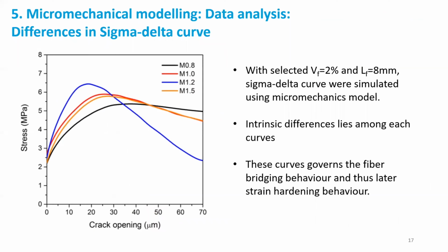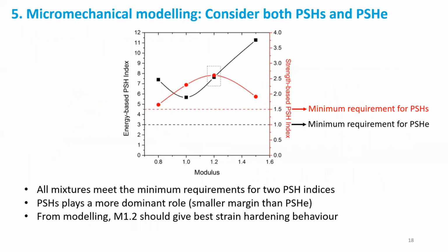Afterwards, we incorporate these two values along with the interface and the matrix properties, and we use micromechanical modeling to calculate the sigma-delta relationship. You can already see that all of the mixtures have very intrinsic differences among them, which means they should have different strain hardening behavior. We also calculate both PSH indices for all mixtures. As you can see here, all mixtures at least meet the minimal requirement for the two PSH indices. However, it seems that the PSH strength plays a more dominant role, since apparently the PSH energy has a larger margin than the PSH strength. And finally, from the modeling, we can already see that the mixture M1.2 should have the best strain hardening behavior, because both of the PSH indices are very high.